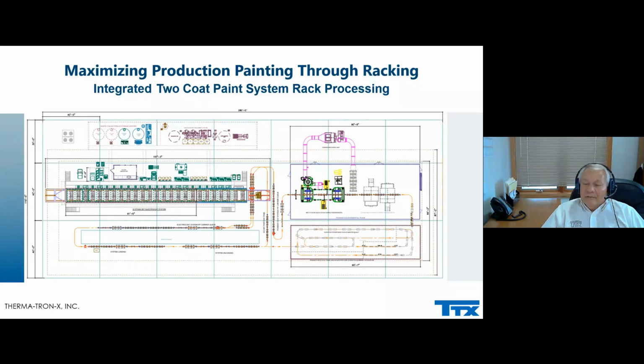If it's all immersion, that's a long system compared to a square transfer. If it's a spray and a combination immersion, you're going to lose some rack density by doing that. So remember, with immersion monorails, you're going to have longer immersion times because of the inclines and declines. With a square transfer, there is less tank volume, less chemicals, more effective.